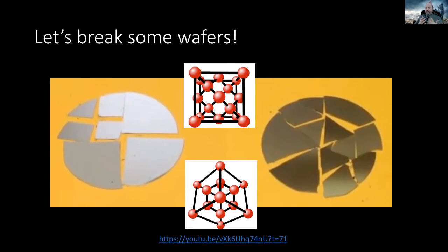We had a case at Philips Semiconductors where we put some power CMOS devices on a 100 wafer set of wafers instead of 111 wafers, and the whole product failed. It didn't behave electrically like it was supposed to. And it took us a while to figure that out, because we looked at how it was made, what the structures looked like. Everything looked normal, except someone figured out, oh, we used the wrong wafers when we started.